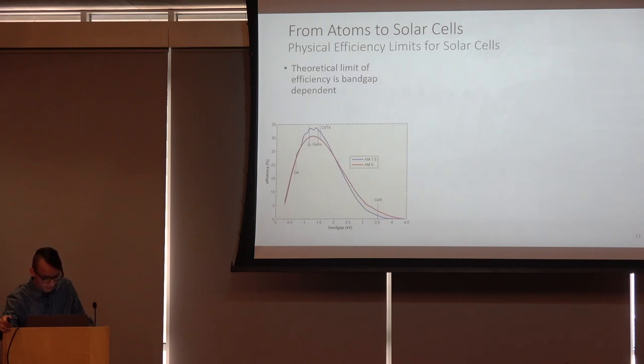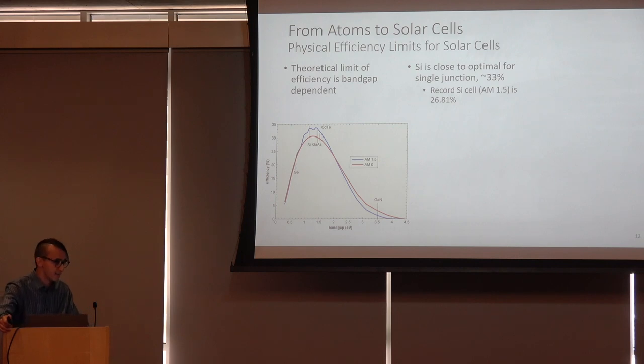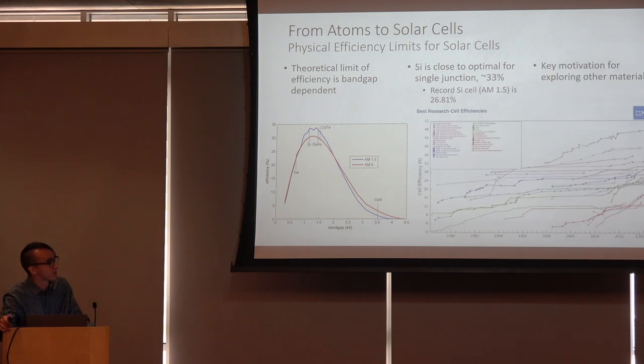For solar cells, particularly single junction solar cells, meaning there's just one of these energetic humps to sort charge at, there are well-established theoretical limits in efficiency, and that's shown in this curve here, particularly the blue one. As you can see, the silicon band gap at 1.1 is pretty close to the optimal band gap for this theoretical limit. The theoretical limit of efficiency for a silicon cell is about 33%, and the record silicon cell today is 26.8%. And so these devices are pretty darn close to perfect. There's not too much room for improvement, and this serves as a key motivation for exploring other solar technologies.